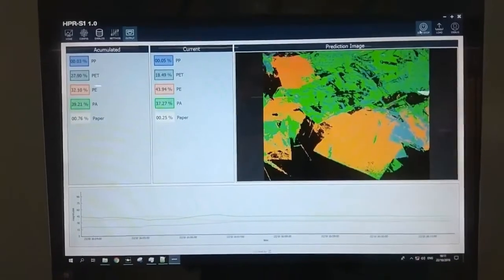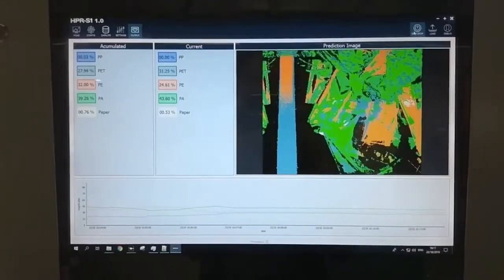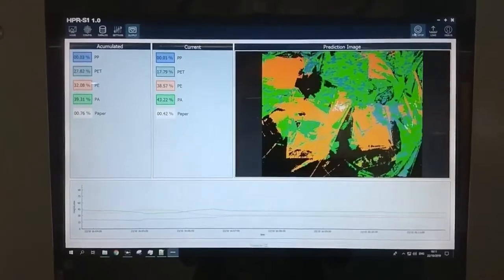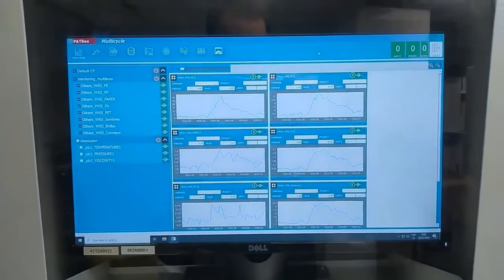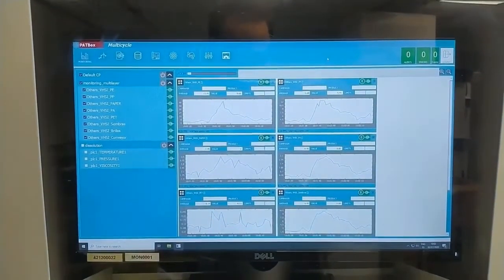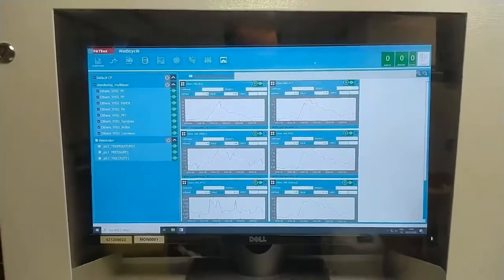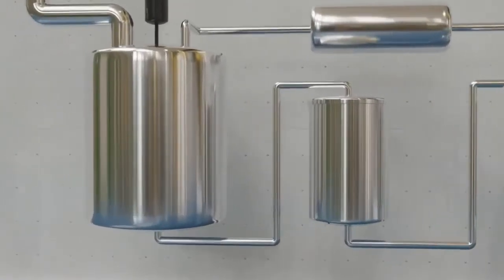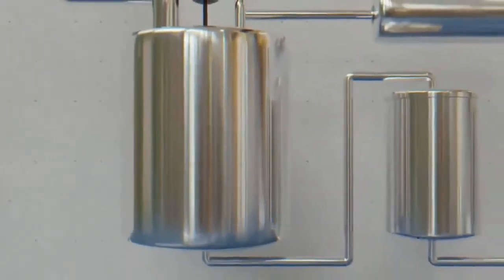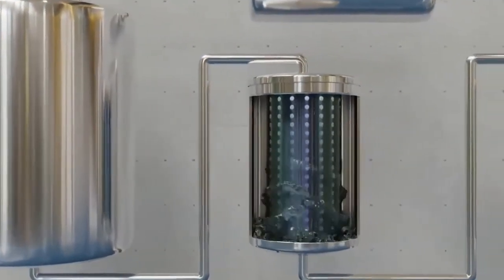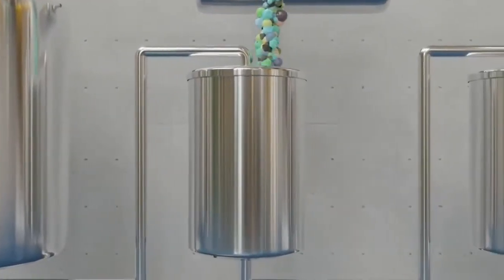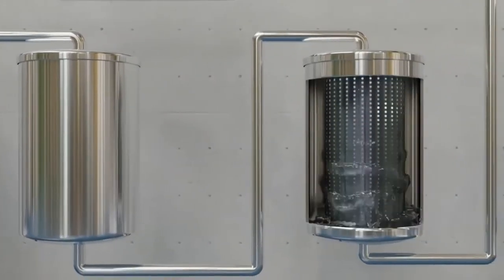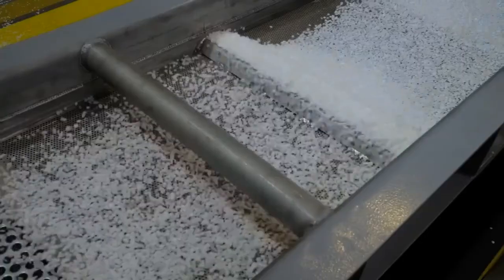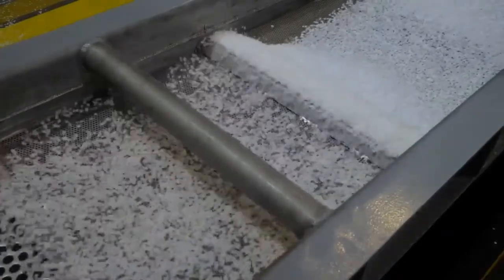The complex spectral information obtained from either near-infrared hyperspectral imaging for flexible packaging waste or laser-induced breakdown spectroscopy for composites is interpreted by the process's control software to determine the best strategy for recovery of target materials. This consists of one or more dissolution steps, depending on the number of target polymers for recovery, with the recovery order determined by the thermal and solubility properties of the polymers. The MultiCycle approach has been demonstrated for a range of commercially relevant plastics, variously incorporating polyethylene, polypropylene, polyamide, and PET.